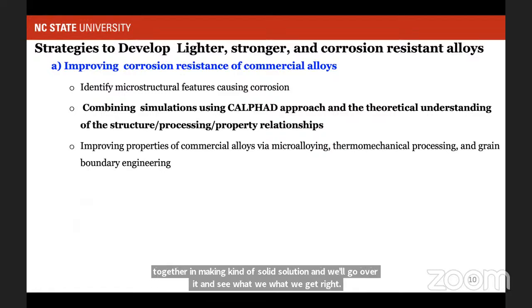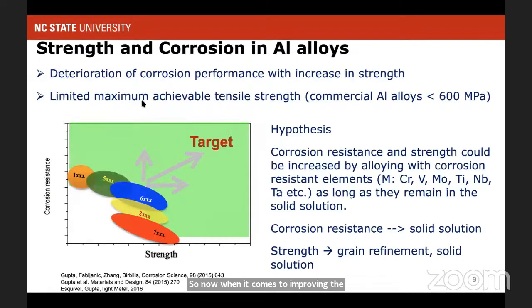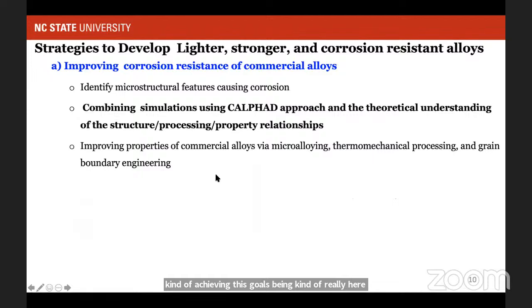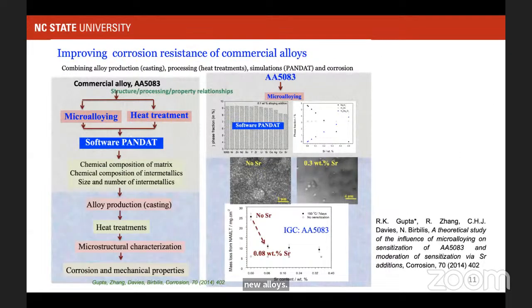So now when it comes to improving the properties and achieving these goals, being really here in the top right end of this graph, we could have two strategies. We can take the commercial alloys and improve their corrosion resistance, right? And the second approach would be making purely new alloys which have really good corrosion resistance. With the approach of improving the corrosion resistance of commercial alloys, we can do that, but the challenge is there. We could increase the corrosion resistance a little bit. We can solve very specific problems, but it becomes very difficult to go beyond the limits of those commercial alloys. Crossing the conventional property limits is difficult.